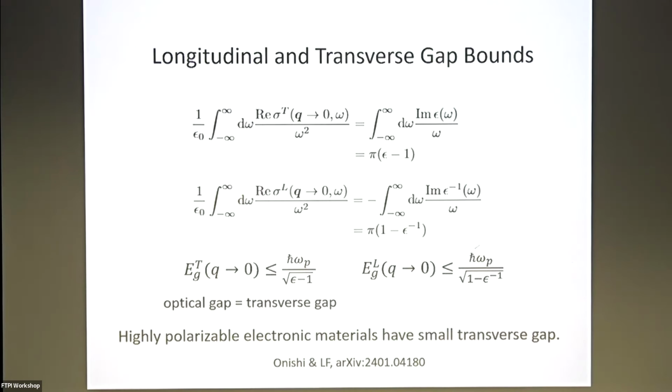Now, in many materials near the ferroelectric condition, it's driven by a soft phonon. In that case, the static dielectric constant can be very large, but that's not the electronic component getting large. So there's a difference. This is the optical gap probing the electronic gap. Therefore, the dielectric constant I've used is the electronic dielectric constant, which in the literature people write as epsilon infinity. What it really means is just the electronic.